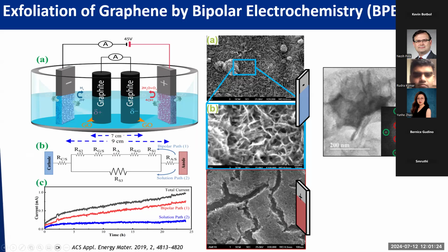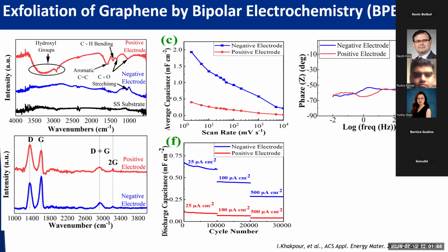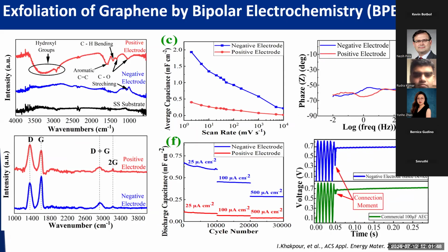self-assembly. You can see the picture here shows this pretty thick layer already deposited on the positive feeding electrode. But at the negative feeding electrode, it's reduced graphene oxide, and it's vertically aligned, so we have more surface area in this case. We did a lot of research on material characterization and electrochemical characterization of this BPE-based graphene. And we found this graphene has a much better quality compared to other graphene, since it's really fresh. It's in situ: you can do exfoliation, deposition, and even reduction at different feeding electrodes. We found for 3D, high surface area graphene vertically aligned on the negative electrode.